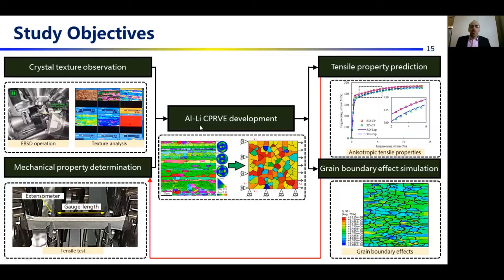In this study, CPRVE or CPFEM models are developed by extracting the microstructure, crystal texture, and grain morphologies from the EBSD process and calibrated by the mechanical properties from the tensile tests. And the developed model can predict the texture-induced anisotropic tensile properties in the rolling and transverse directions and the grain boundary effects on the stress-strain heterogeneity in the CPFEM model.